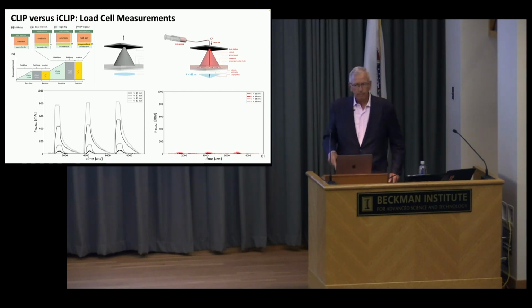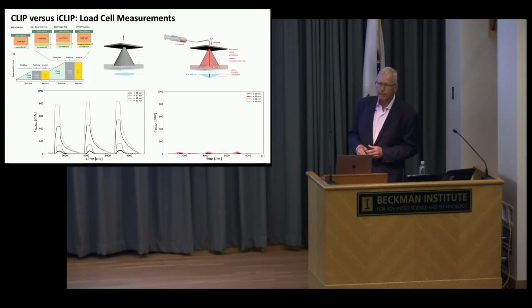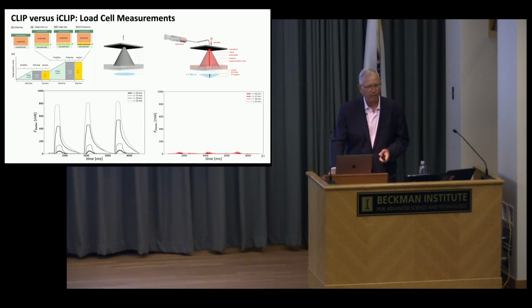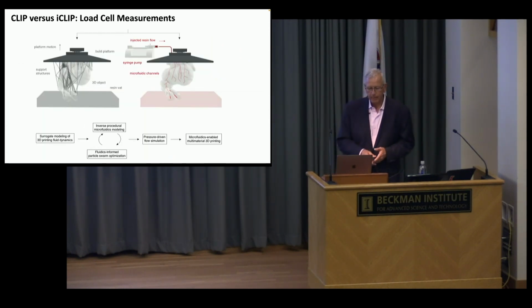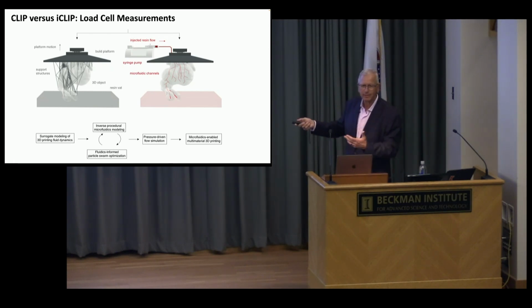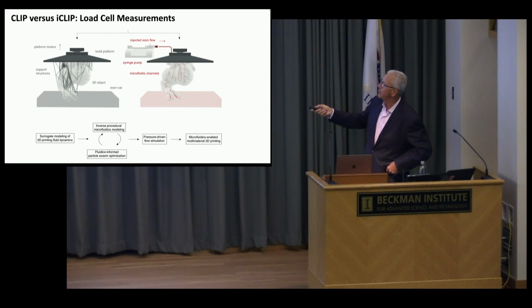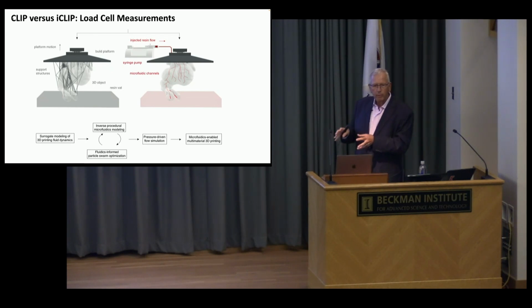Well, when you inject liquid, that goes away. In fact, it can be like a rocket ship. You have to hold it down, right? And this allows printing to go way faster. And you can eliminate the supports. You saw those dentures with lots of supports on them as it was coming out of the printer. Here's the Stanford Bunny. It's got some history, and I don't even know, I'm a chemist, but everyone revels in the Stanford Bunny. All the supports to make it. When you inject liquid and you avoid the adhesion, and you innervate the part with these fluidic channels, you can eliminate the need for these supports.